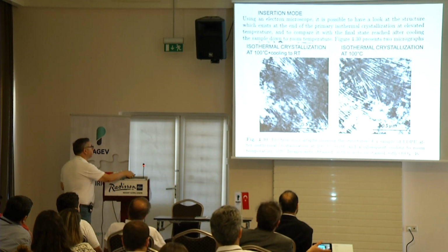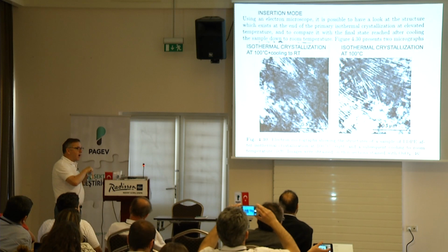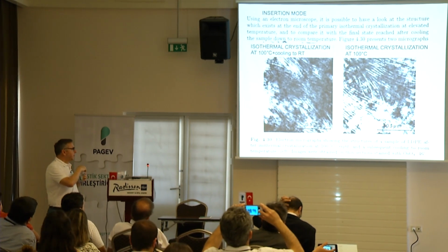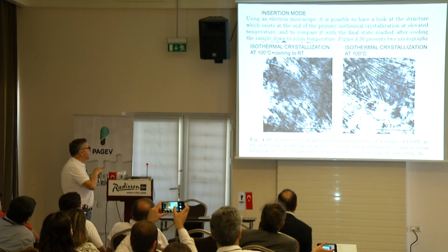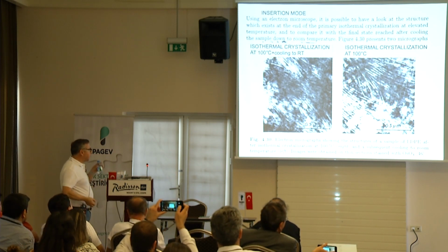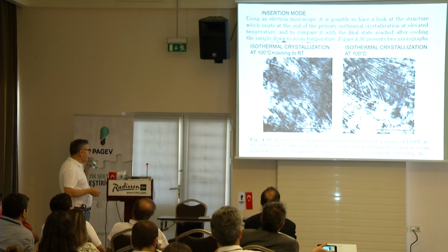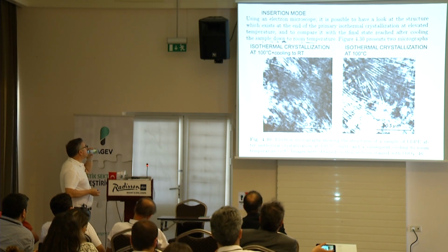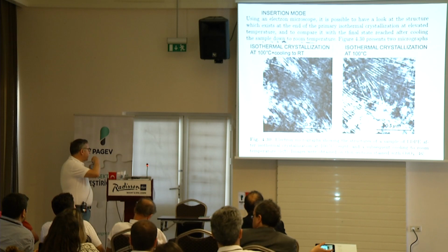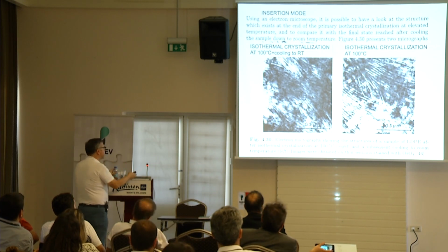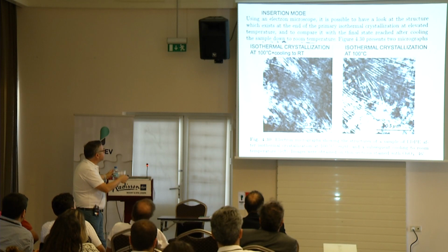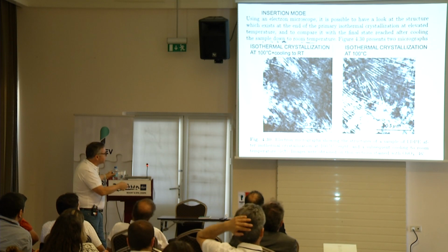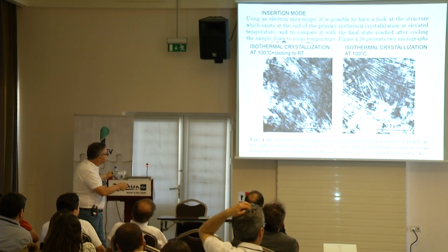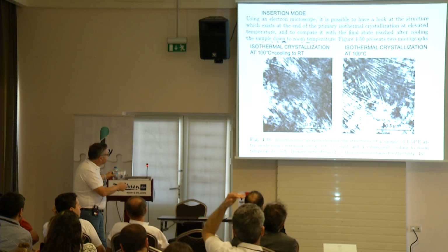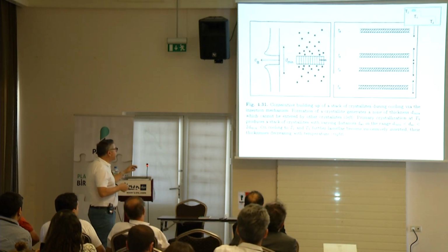All right. Now, what happens during secondary crystallization is that people have studied it. They call it an insertion mode, and I'll show you. Secondary crystallization: this is 100 degrees plus cooling to room temperature, and this is isothermal at 100 degrees for a long time. You can see the contrast between the two. This has more uniform lamella. This has a more varied distribution of lamella sizes. So people have done this.